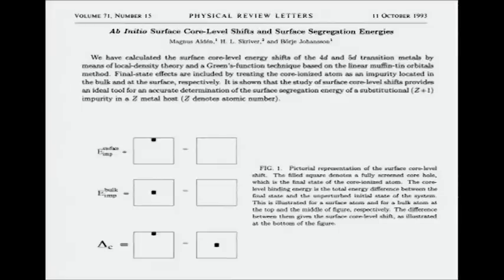And the schematic is very pretty, because here you see the initial state, the ground state, the solid. Here's the final state for the surface atom. So we've now got a core ionized atom here. So this is what I measure in the photoemission from this state, the difference between the initial state and the final state. Here it is in the bulk. And so, of course, the surface core level shift is just the difference between these two, and the difference between those two is just the segregation energy, the energy of segregation of the Z plus 1 atom to the surface, because the final state we can represent in the fully screened state as a Z plus 1 atom. So it's a nice illustration of the effect.